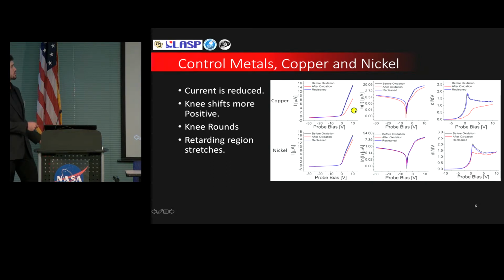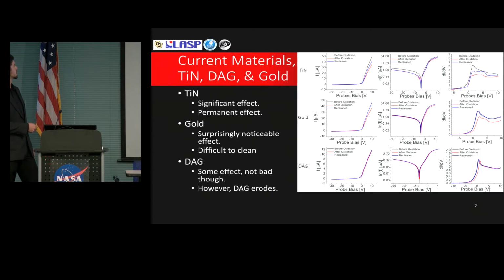We see that the IV curve shifts to the right. The knee here, which measures the plasma potential, also shifts, and there's a stretching of the retarding region where you would measure the temperature. So in general, the knee shifts more positive, the knee rounds, and the retarding region stretches. This is somewhat corresponding to what we would expect for a resistor in the circuit. If there is a resistive layer, we'd expect something of this order.